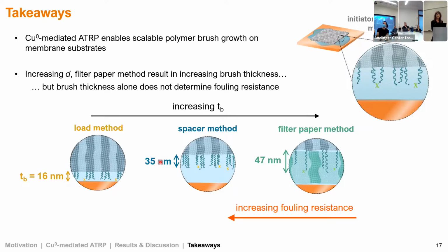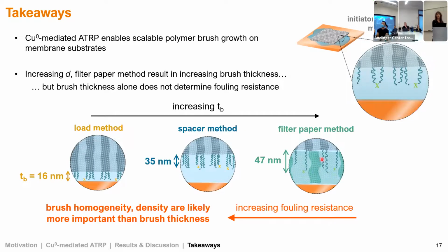Yeah, I'm thinking it's either lower density or that there are more defects present for this filter paper method. When we insert a material with its own surface roughness and porosity, in some areas we have a distance equal to the thickness of the pore, but in other areas we may have contact between the material and the membrane. In those areas, we're likely getting much thinner brushes, or, as I illustrated here, maybe no brush growth. So it's probably a lower density, either at a macro scale or a micro scale,